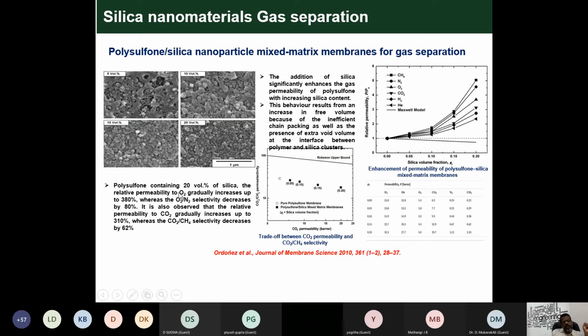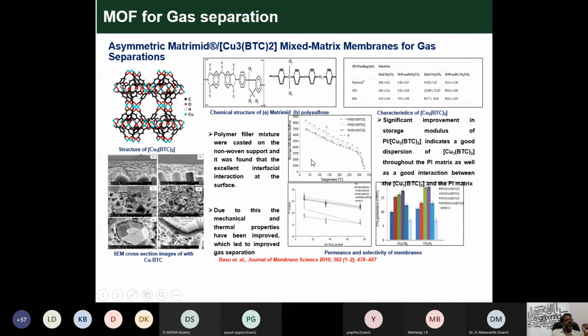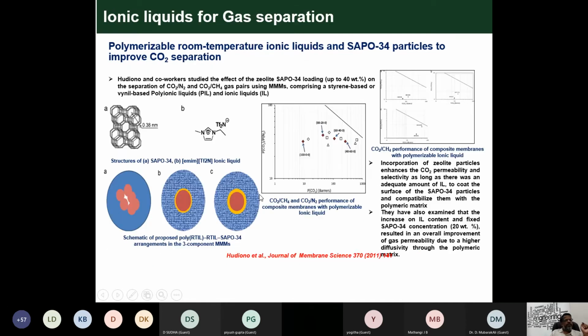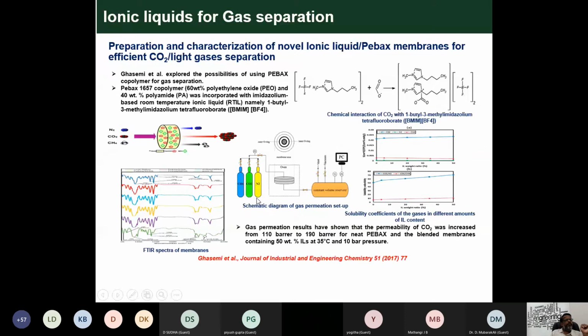Then we compared the performance with silica and MOF membranes for gas separations. This is one of the works by Basu from IIT Delhi. They developed different MOF membranes for gas separation, especially carbon dioxide separation. Ionic liquid is a liquid, and when incorporated into the polymer, it creates a sponge-like interconnectivity between the polymer phase and the liquid phase.